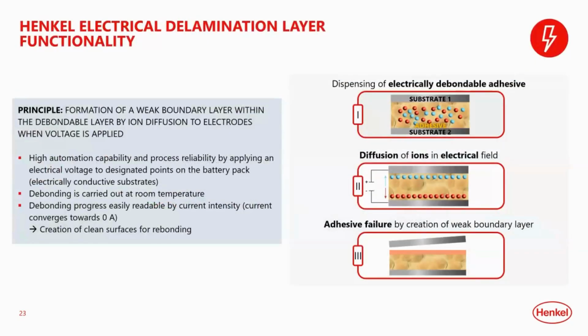A little bit of a deeper dive into how electrical delamination works. We're weakening the bond by ion diffusion, which is initiated by applying voltage to the two electrically conductive substrates in contact with the bond line. So it's crucial that the two substrates are electrically conductive, of course.